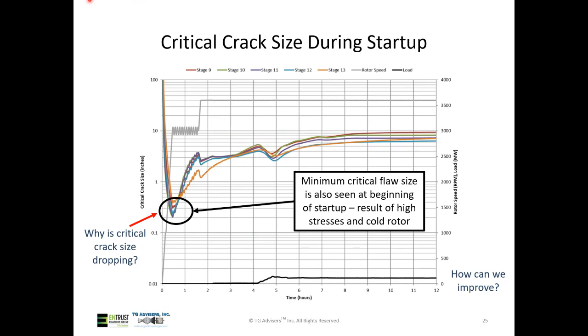So ultimately, what we get to with all this modeling is a critical crack size. And essentially it tells us how big a flaw can I withstand before I'm concerned about a potential rotor burst. Now, there is a fair amount of conservative assumptions that go into this, so you probably don't want to look at the absolute value and get too hung up on that, but you can look at the relative difference pre and post optimization.